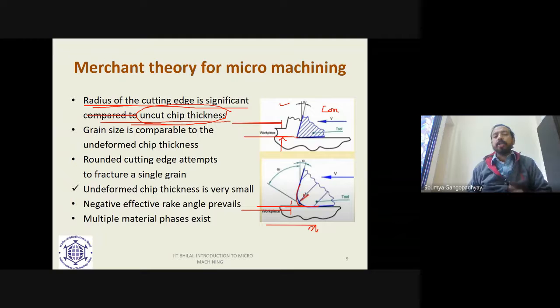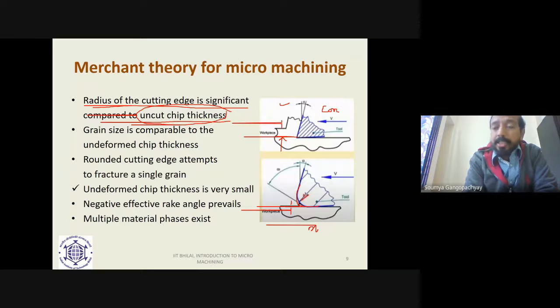Why are we suddenly putting a lot of emphasis on uncut chip thickness? The answer is very simple, but very important to understand as well. The value of the edge radius, I repeat, the value of the edge radius and uncut chip thickness are of the same order of magnitude in micro cutting. In micro cutting, the edge radius of the tool is of the order of 2 to 3 micron. Even the uncut chip thickness is also around 1 to 5 micron.